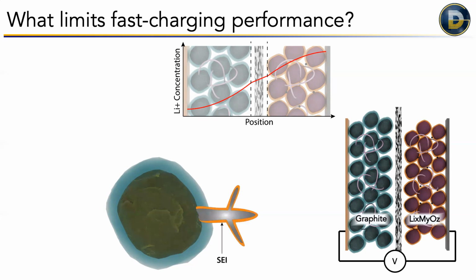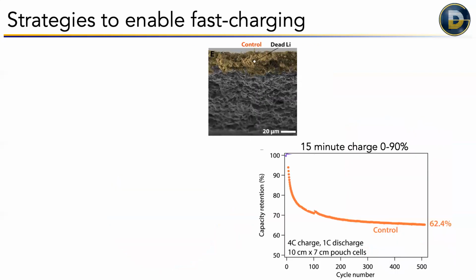But now this is no longer protected by that passivation shell, so then it continues to grow, it forms more SEI on top of the lithium metal, which again consumes liquid electrolyte, and you only have a finite amount. And because lithium metal is so reactive, we can't actually strip all of it back when we discharge our battery. So you get these isolated little pockets of lithium that we call dead lithium, and that's directly reducing the capacity of your battery.